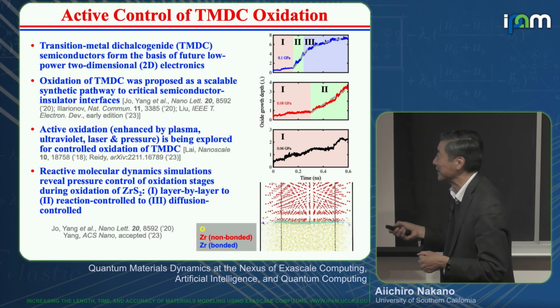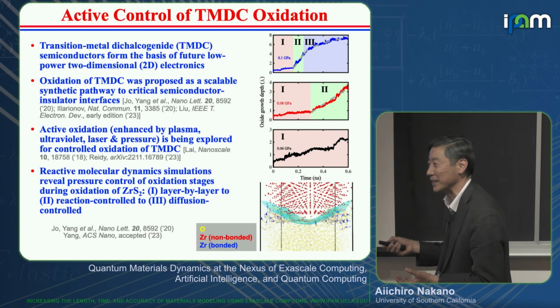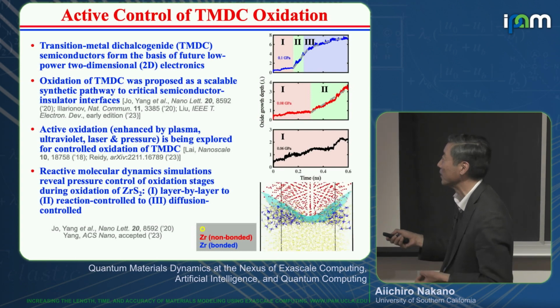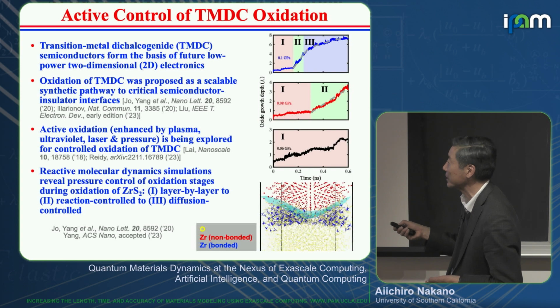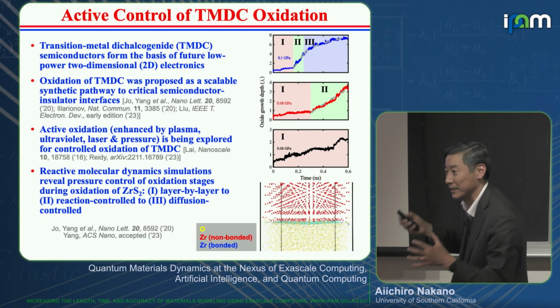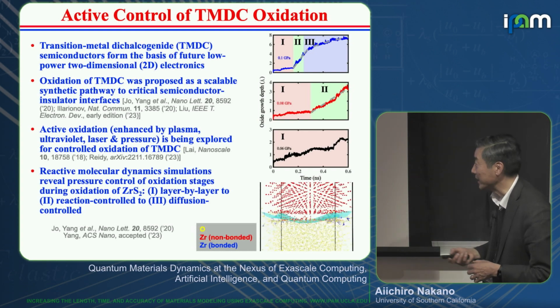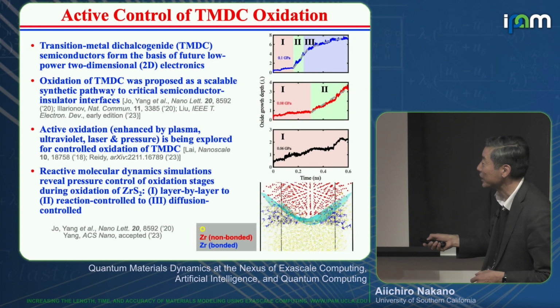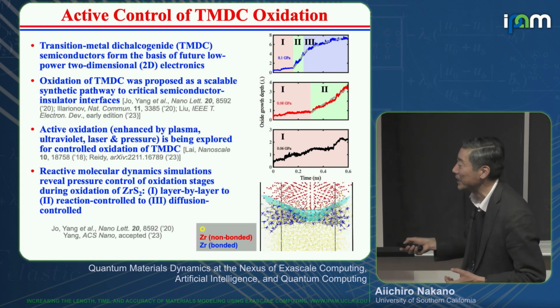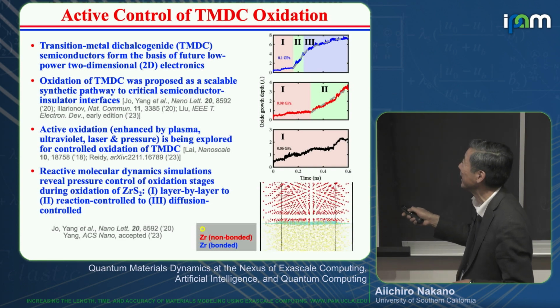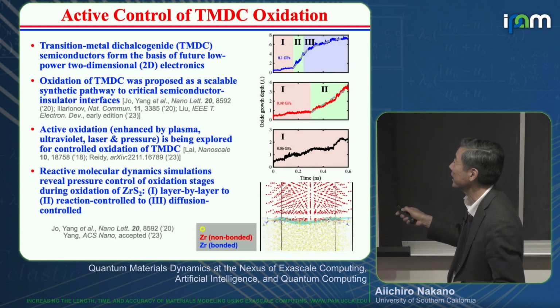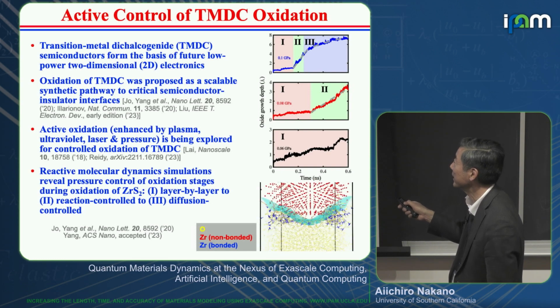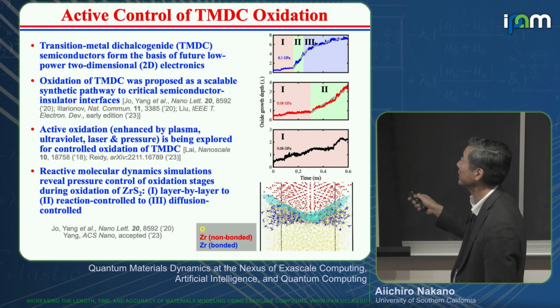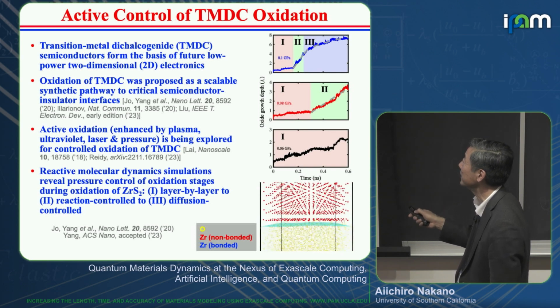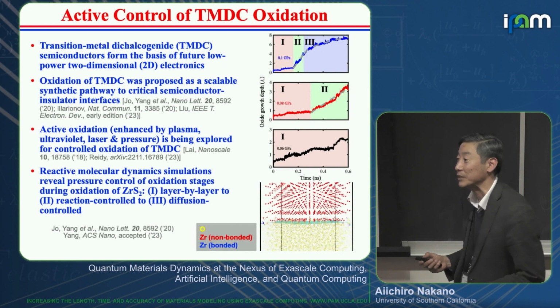Moreover, he and some other people propose not just passive oxidation, but active oxidation as a quality control. Active means oxidation enhanced by plasma, UV, or laser, or pressure, like in a pressure chamber. So we did a reactive molecular dynamics simulation to show the pressure control of active oxidation. We found that this 2D oxidation proceeds in a stepwise, layer-by-layer, slow oxidation, then reaction-controlled linear oxidation, and then diffusion-controlled parabolic oxidation. Those three stages can be controlled by different pressure. So that's actively controlling for future 2D electronics.